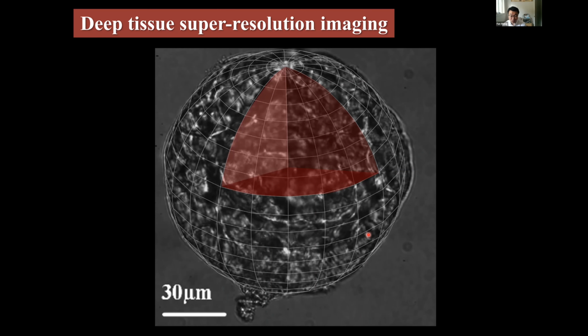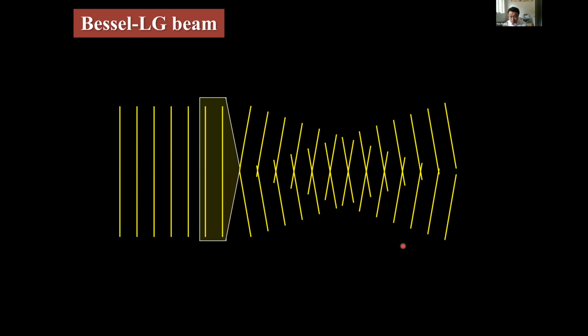I mean, it works, but only for about 20 micrometer, it won't go through 100 micrometer. So this is why we want to expand our method a little bit to make it work on this organoid sample. So what we did is just combine with the Bessel beam, and our collaborator from Peking University did similar things, but for STED. So over here, I want to introduce the Bessel beam. So Bessel beam is some interference-based beam. It's really interesting. All the beams, when they come through this axicon or something, they change the angle, and the focus is formed by the interference of the different directions of the beam.